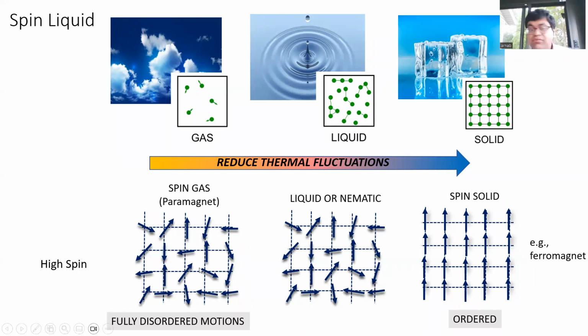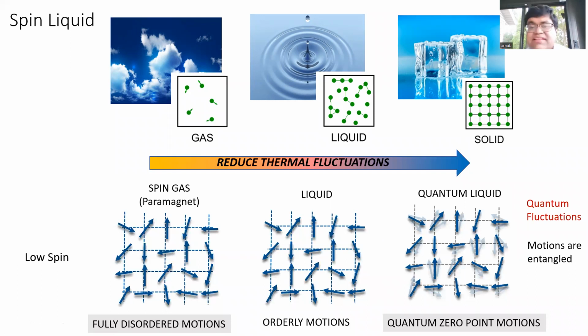At higher temperature, you have fully disordered motions. So you have a high degree of fluctuations, and you get what is called the paramagnetic state, which is essentially a spin gas state. Then you can get to a liquid or nematic phase when the spins start to interact between themselves. And then finally, when you freeze all the spins out at lower temperatures, you get this spin solid or ordered phase, and ferromagnetism is an excellent example of that. But what happens in a quantum spin liquid is that even when you decrease the temperature completely, you still get a huge amount of quantum fluctuations, and then the motions are all entangled.